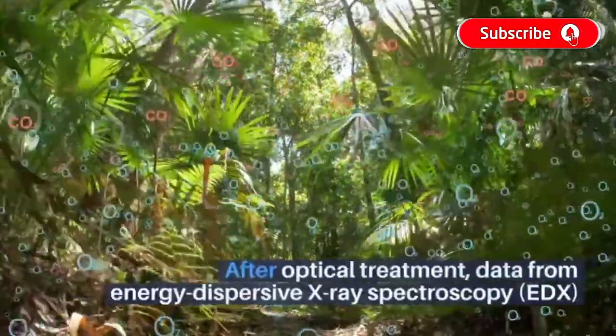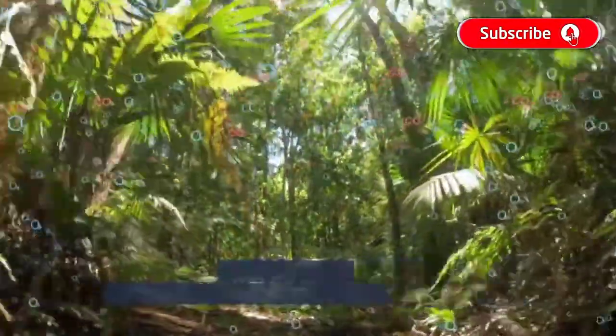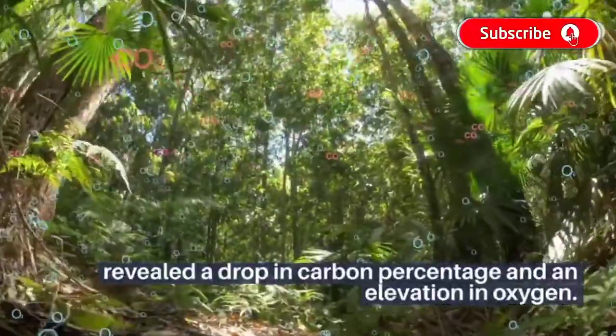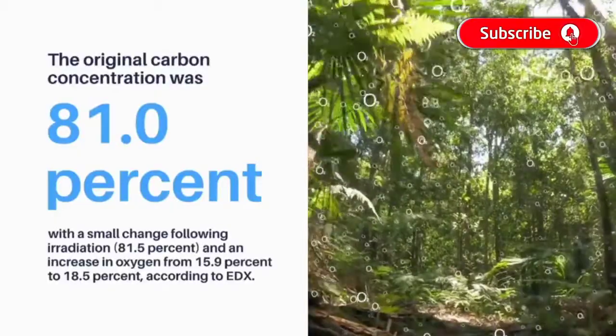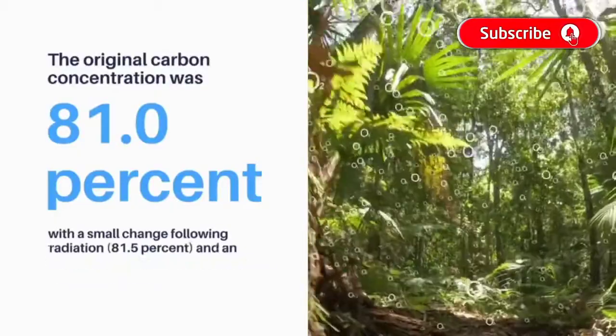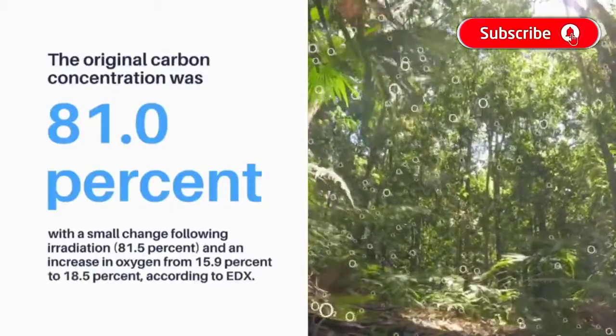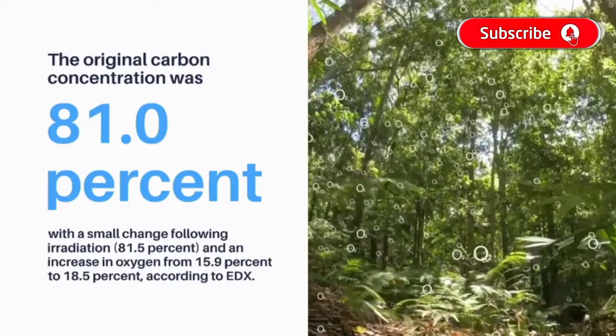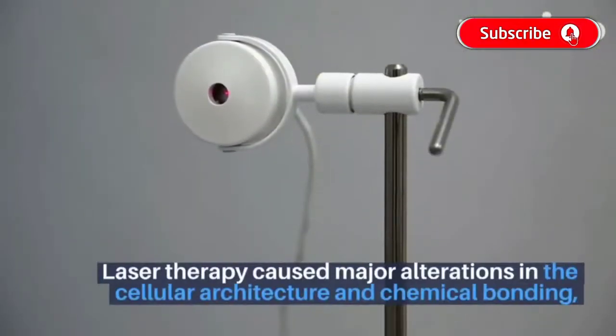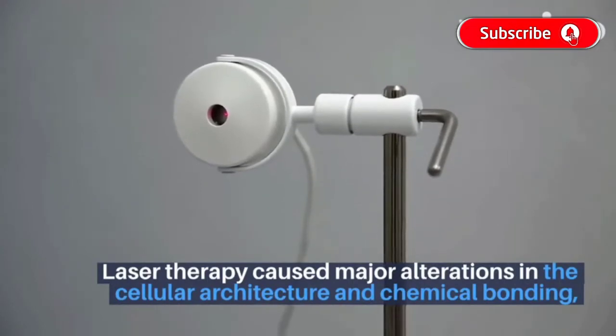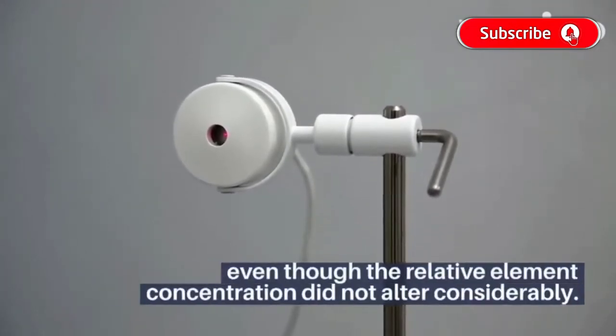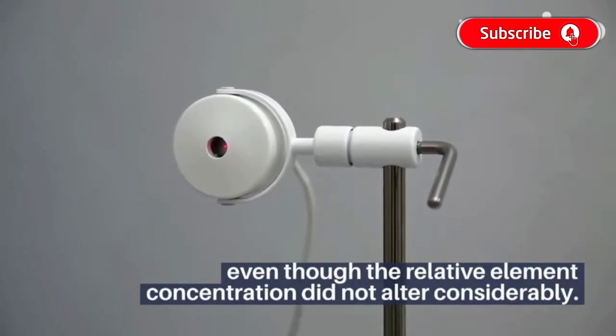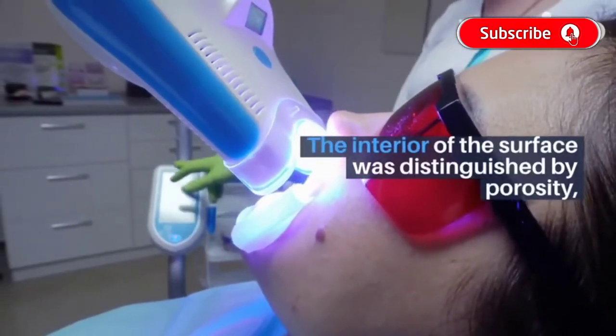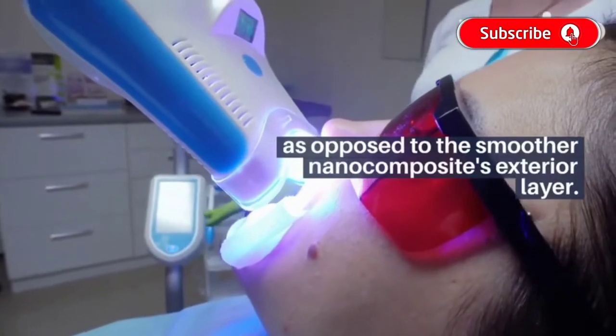After optical treatment, data from energy dispersive X-ray spectroscopy revealed a slight increase in carbon percentage and an elevation in oxygen. The original carbon concentration was 81.0% with a small change following irradiation and an increase in oxygen from 15.9% to 18.5%. According to EDX, laser therapy caused major alterations in the cellular architecture and chemical bonding. Even though the relative element concentration did not alter considerably, the interior of the surface was distinguished by porosity, as opposed to the smoother nanocomposite's exterior layer.